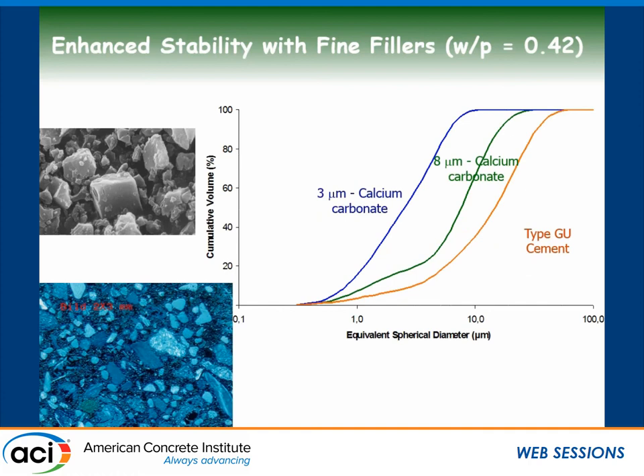Some of the factors contributing to the surface settlements, and the previous presenter expanded on that, here we have the use of fillers. When we do SCC, we have to use a lot of binder, a lot of powder, I should say. In some cases, we use supplementary cementitious materials, and in some cases, we use that or fillers. The type of filler is very important to densify and increase rheology. This is the limestone filler, calcium carbonate.